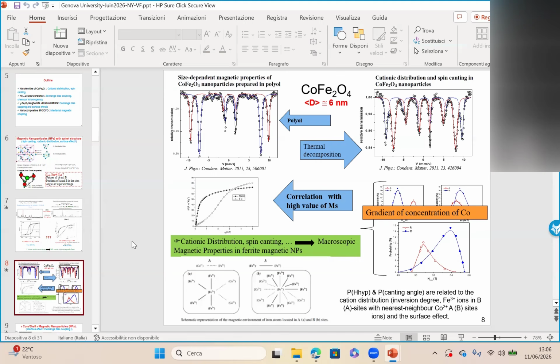The main problem with these samples is that Alberto wanted 2 grams, so 1 gram to do neutron diffraction. And for this reason, we needed to do self-combustion. That is not the most controlled synthesis, as Pierre knows very well. But it was the only synthesis method that allowed us to do this comparison. And this paper, after 15 years, is still really well cited.